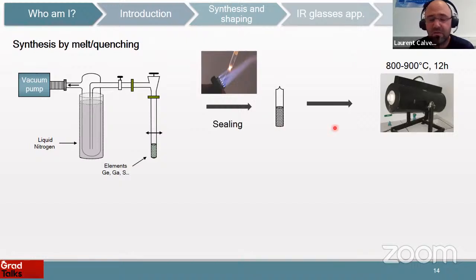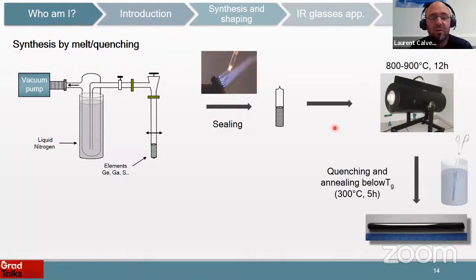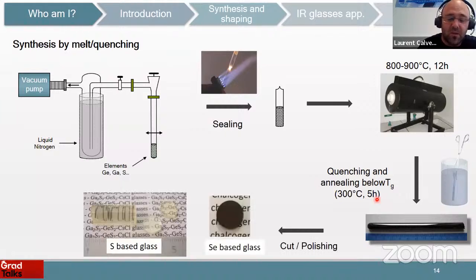And for all the glasses, it's always the same thing. You have to cool it down very fast. It's what is called quenching. So it will go from 900 degrees C to about 300 degrees C in 3 or 4 seconds. And then, because doing this you get a lot of mechanical constraints, you have to anneal the glass around the glass transition temperature to relax the constraints. You will cut it into different pieces, you will polish it, and at the end, you will have this kind of pieces of selenide glasses or sulfide glasses. So it's pretty long to get a glass. It's like 2-3 days.